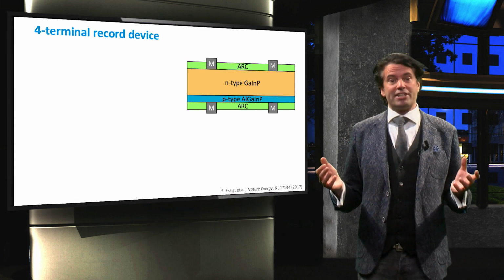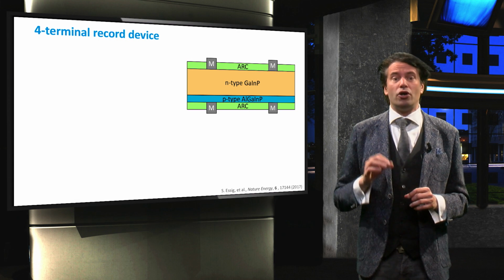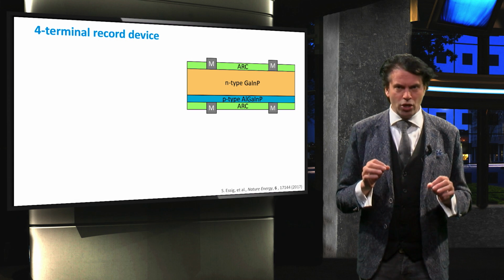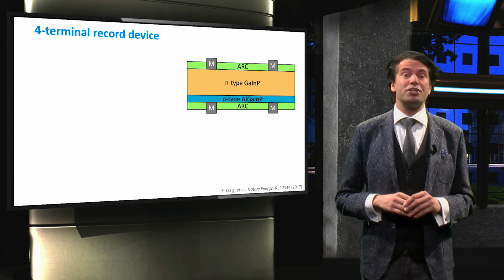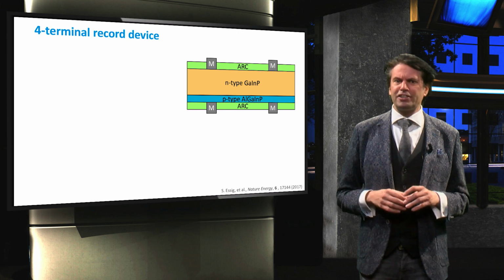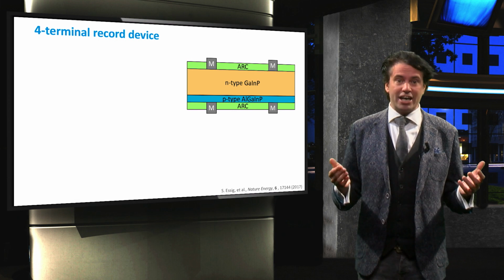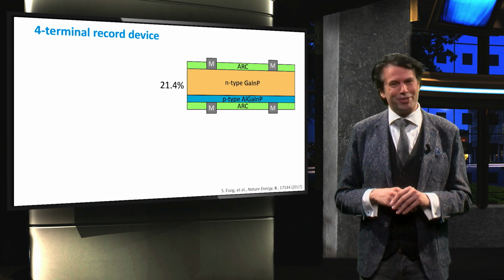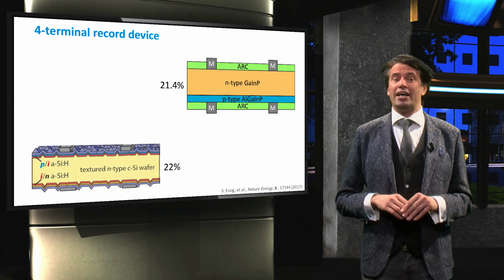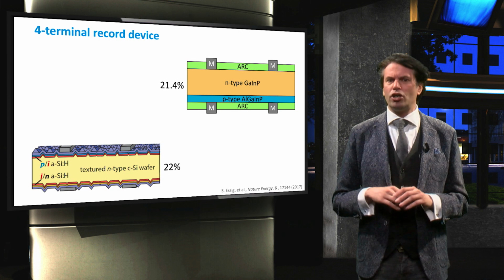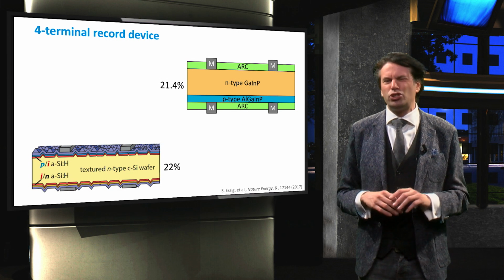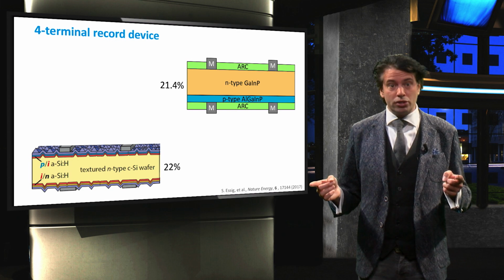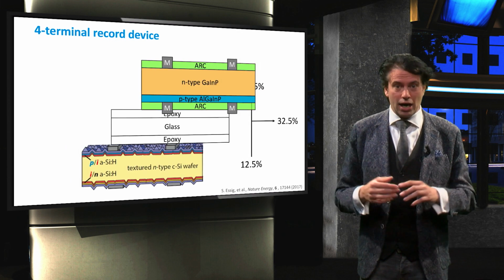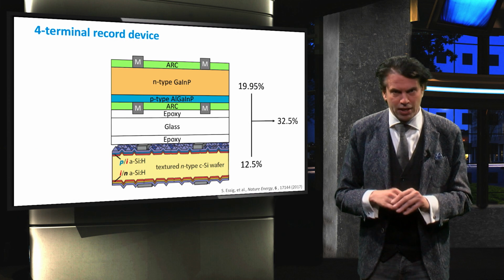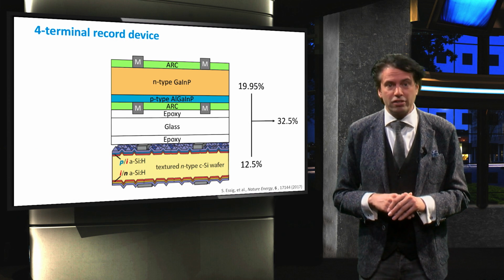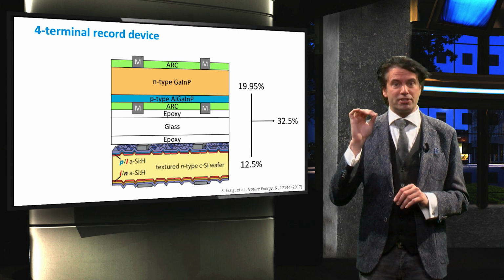The top cell, from which we can see a simplified version, is based on a gallium-indium phosphide cell with a near-ideal band gap of 1.8 electron volt. The record efficiency obtained with the cell in a single junction device is 21.4%. For the bottom cell, a HIT structure is chosen which exhibits a single junction efficiency of approximately 22%. These two cells were attached to a glass slide by an epoxy adhesive. The resulting device exhibits a record efficiency of 32.5%.